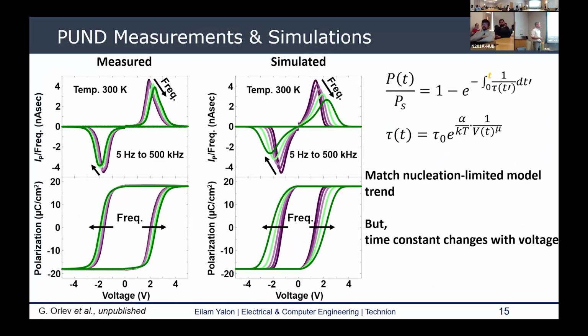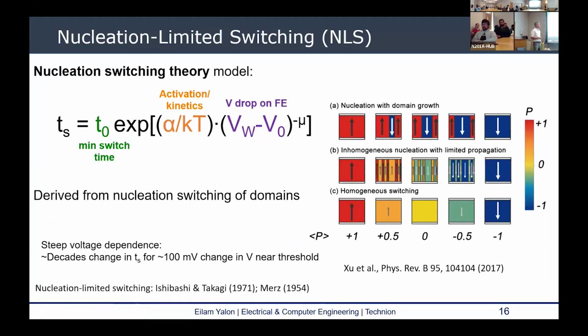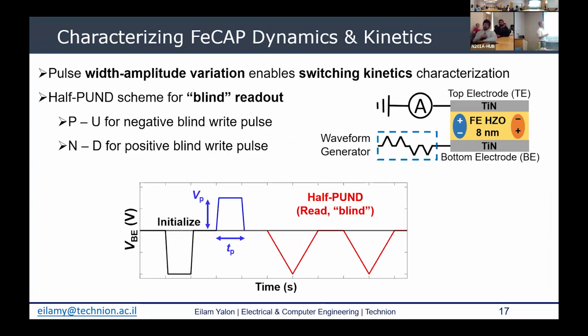So a better measurement to look at switching kinetics would be to decouple the voltage from the time. What we're doing next is a modification to that measurement, where we again first initialize the film to a known state, for example, with negative voltage. Then we apply a rectangular pulse, where we can decouple pulse width and voltage amplitude.